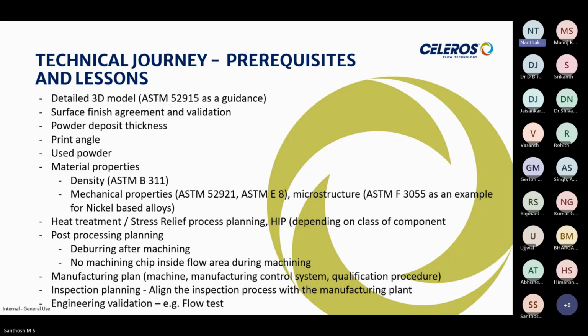So we are familiar with the material properties of those processes, but here we need to be careful about the material properties. So we insisted and discussed density, because in the end the component should be dense enough, as this is a process which can have voids. So density was a key factor. And again, there is an ASTM standard referred to here, ASTM B311. And for mechanical properties, there are two standards here, ASTM 52921 and ASTM E8.